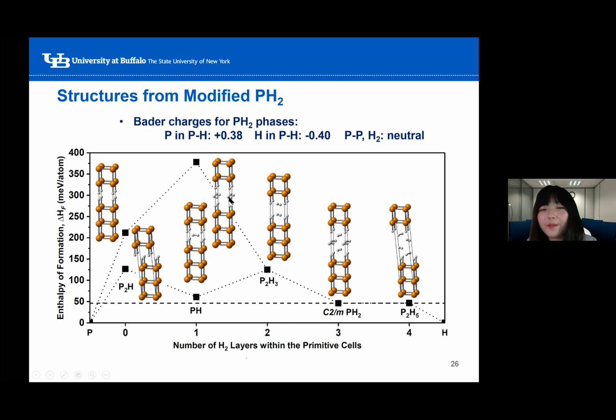destabilizes the structure. We also tried adding extra layers into the PH2 phase and found that the new structure P2H5 has a similar enthalpy of formation as the original PH2. So we believe that the role of the molecular hydrogen layers is to reduce the Coulomb repulsion between the negatively charged atomic hydrogens that are attached to phosphorus. And the stacking fashion of the layers is important.